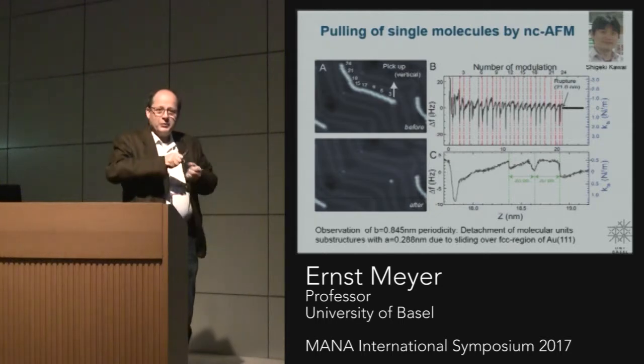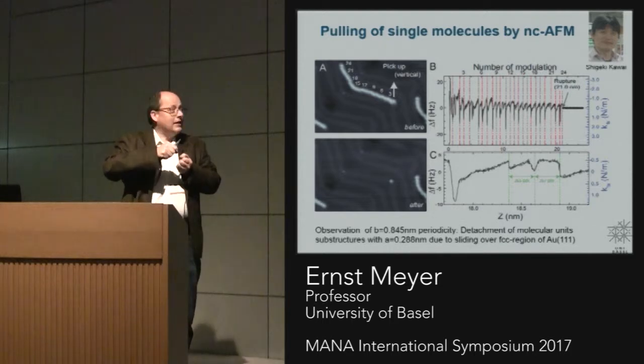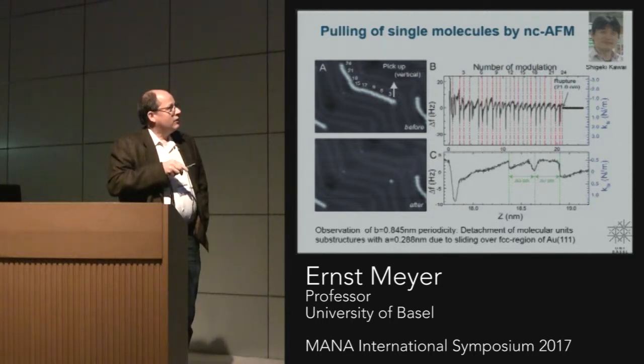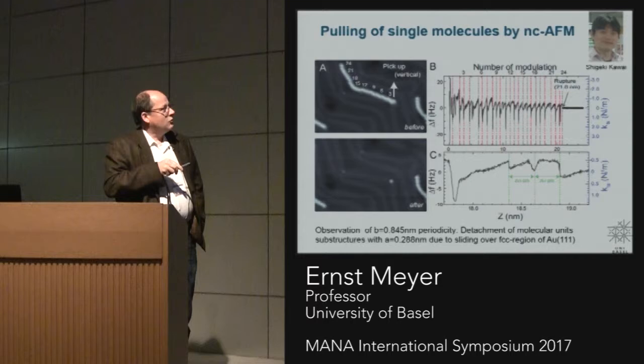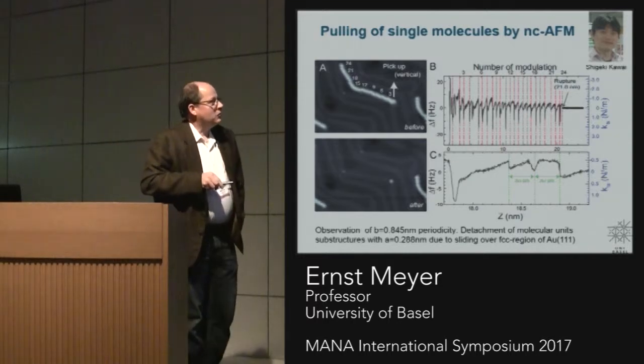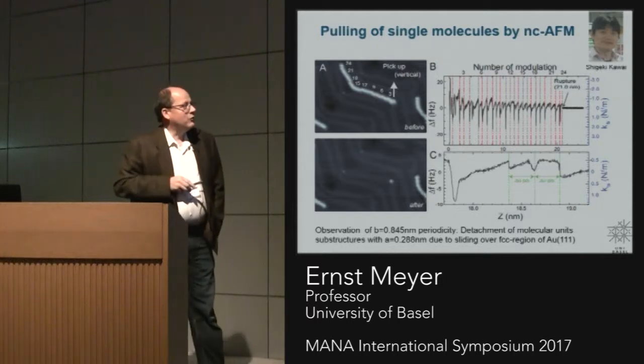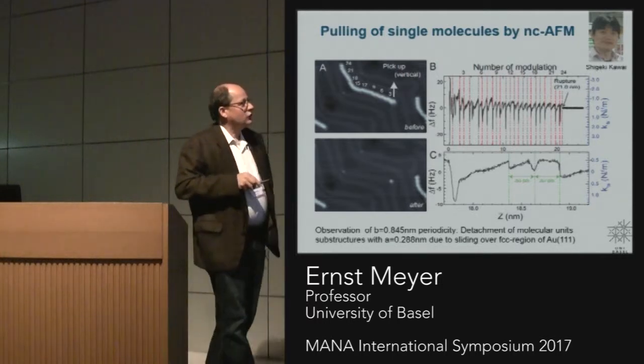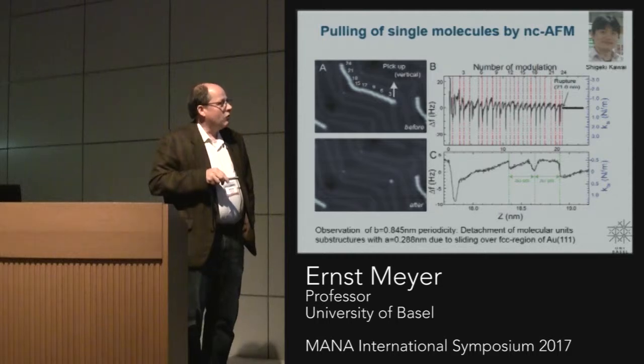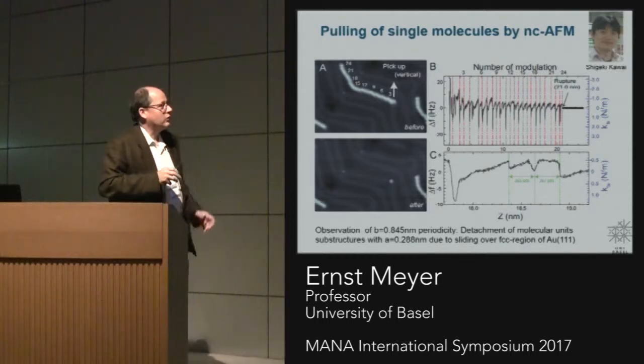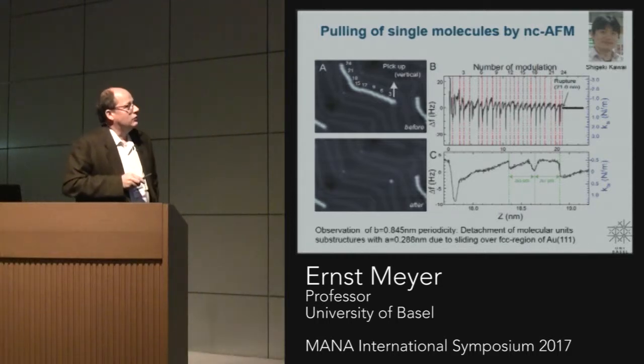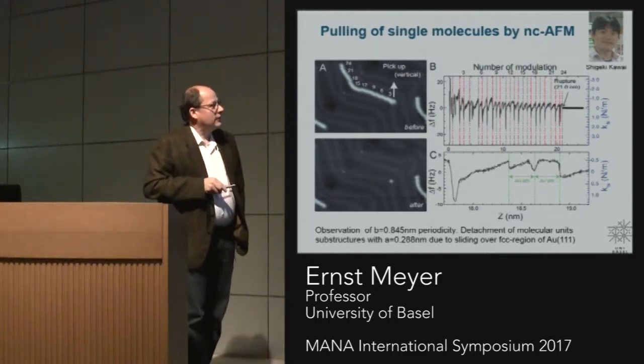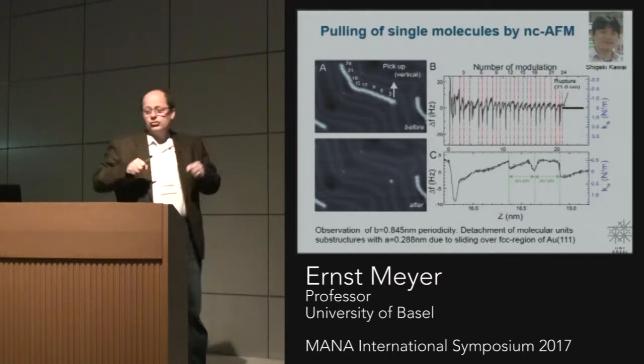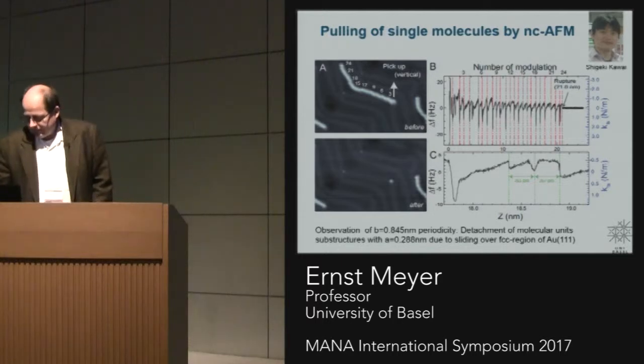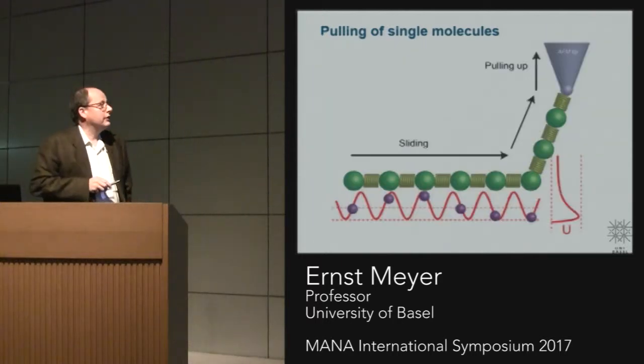And so it's not a peeling in that sense, but you move upwards, and the wire also moves along the surface. And that motion gives you then some lateral forces or some frictional forces, which are relatively small and also not regular in this case, because the contact is not completely commensurate, but they can be related to this motion. So to understand a bit further, we also need some modeling here.